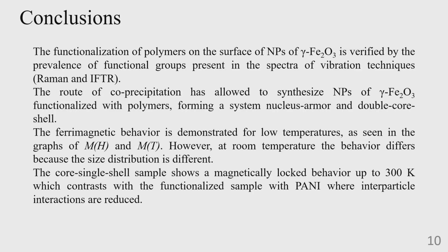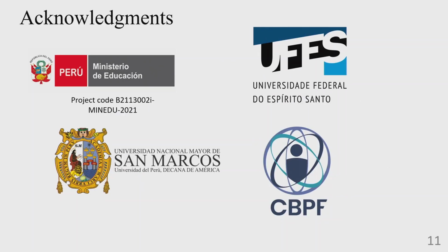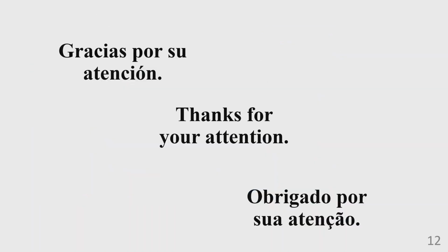The core single shell samples show magnetic blocked behavior up to 300 K, the room temperature, which contrasts with the functionalized sample with PANI, where interparticle interaction is reduced. Well, that is all for now. I acknowledge and am grateful to the Peru Ministry of Education, UFES, San Marcos University, and CBPF too. Thank you.